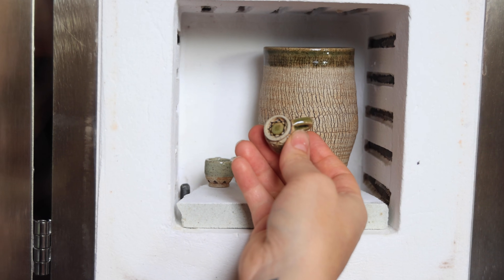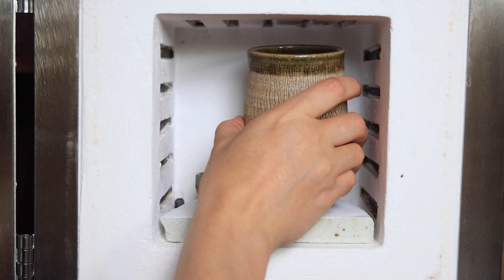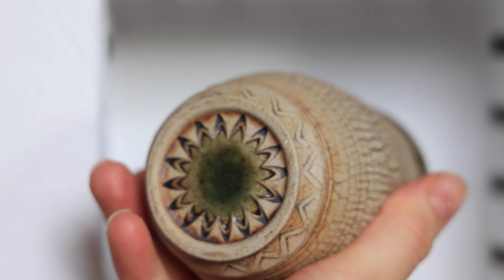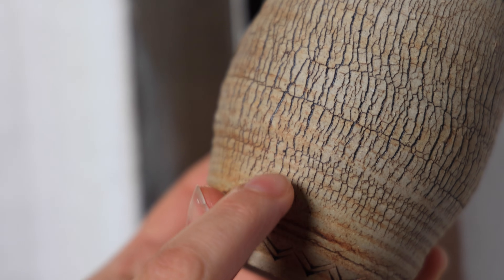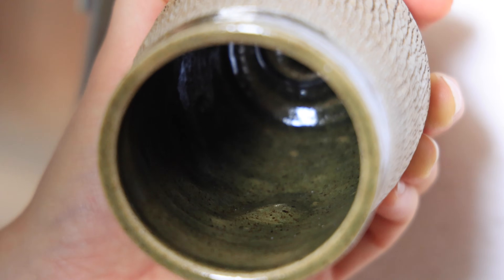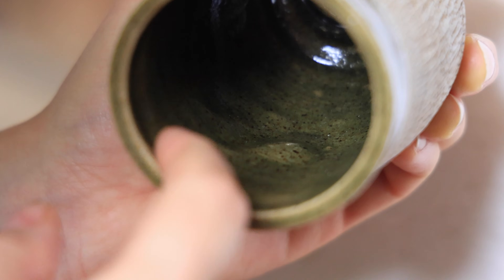I'm happy with how the little pieces turned out, but with this bigger cup — and it could be the clay body — I really have to experiment with what types of clay would work with such a rapid firing. This piece won't work as a cup anymore because there were some air bubbles, probably from gases expanding. There's a lot of chemical reactions going on with very little time for escape. Also, I did bring this to the fullest temperature — you could probably fire at lower temperatures and it would work amazingly.